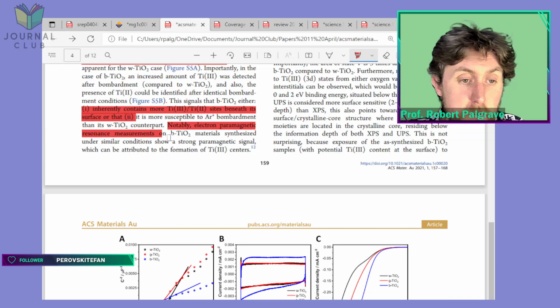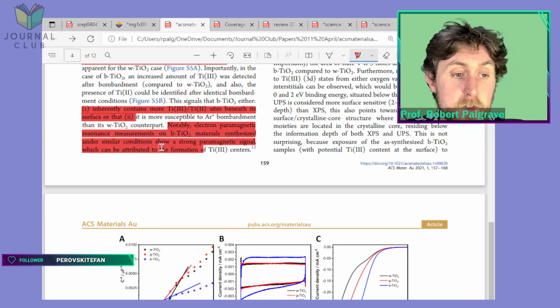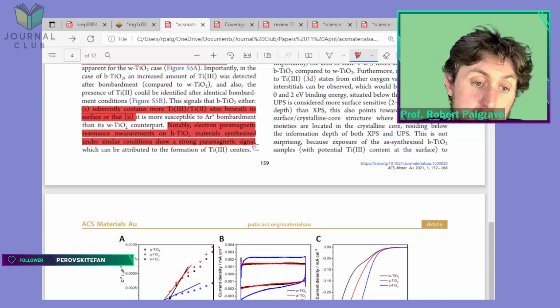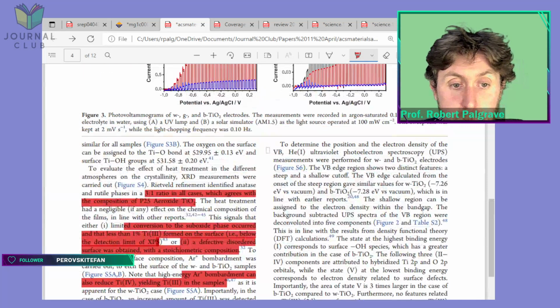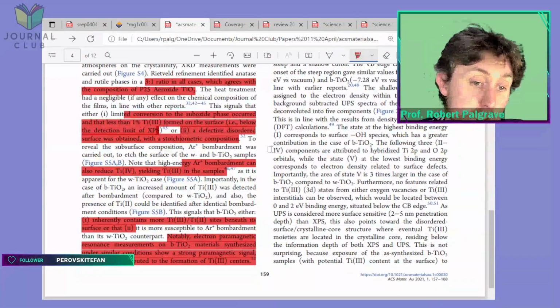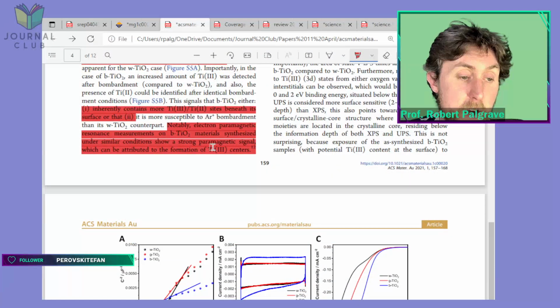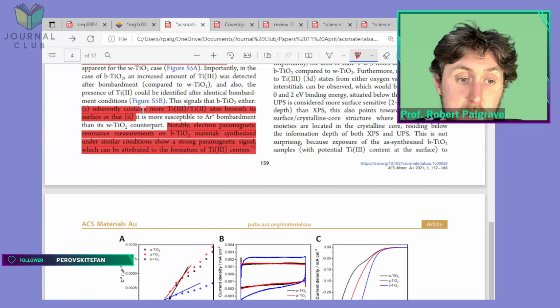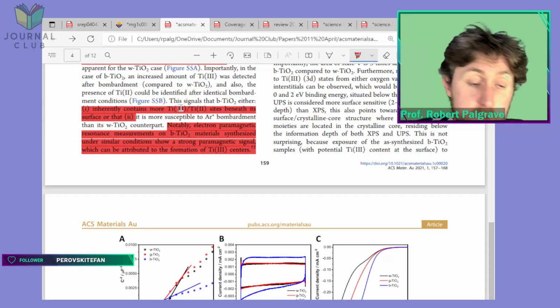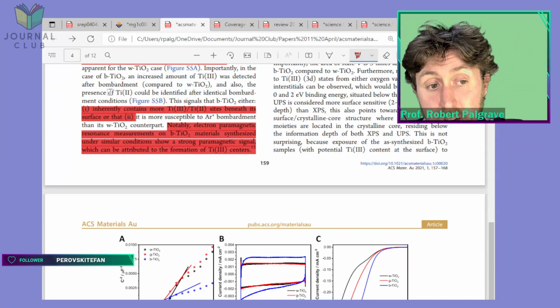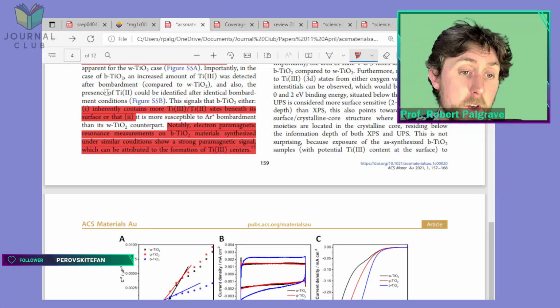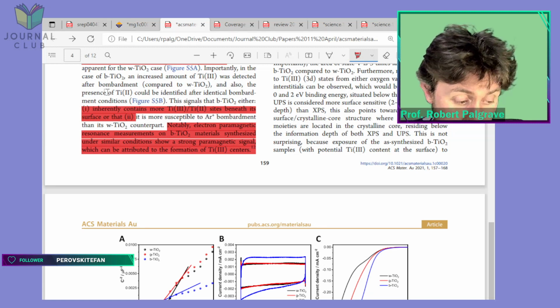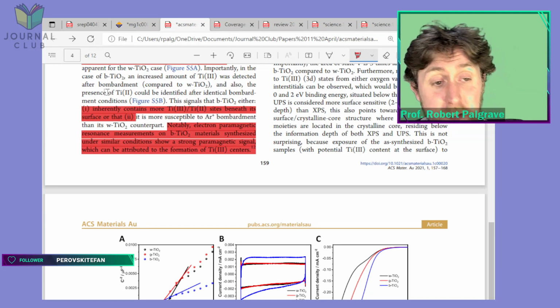Notably, electron paramagnetic resonance measurements on black TiO2 material synthesized under similar conditions show a strong paramagnetic signal, which can be attributed to formation of Ti3+ centers. I guess they don't say it outright, but that supports the first conclusion, that the Ti3+ is there, but it's just hidden underneath an oxidized layer. Now the problem with that is that XPS is surface sensitive, but it's not that surface sensitive. You're still going to look about 4 to 5 nanometers, maybe even further into the material.